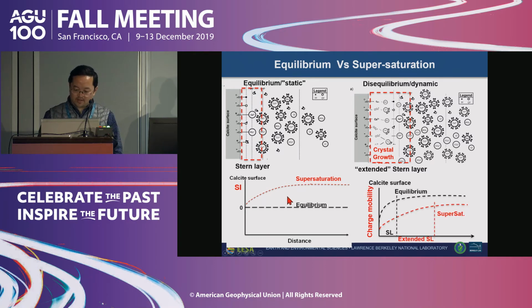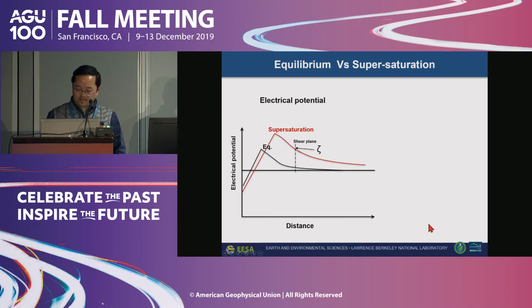In terms of ion mobility, you can actually compare these two situations. Under equilibrium condition, you have a shorter distance where the mobility is decreased because of the bonding to the surface. But under supersaturation condition, because of this growth of the mineral, you likely have this extended stern layer thickness and also reduced mobility because of the higher concentration of ions that are giving you this heightened impedance response.